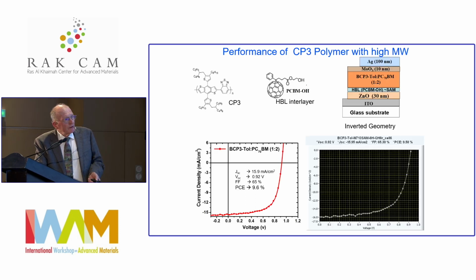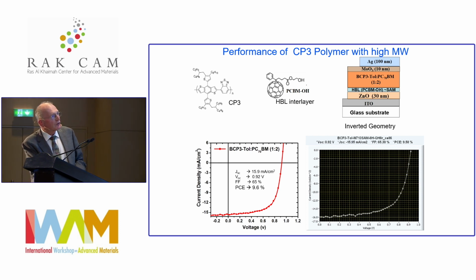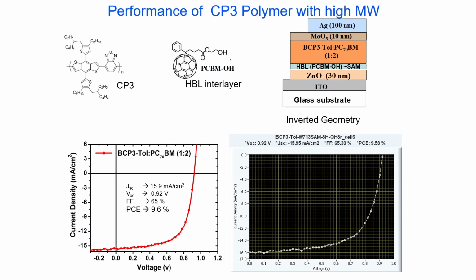And we pretty much made it, although the average efficiency was around 9.6%. But here's the structure of the donor polymer on the left. The fullerene is a hole blocking layer here. That's not the acceptor polymer. It's a hole blocking layer to facilitate negative charge extraction in this direction. And a blend of then the fullerene and the donor polymer. And we reached 10%, but the statistical average was 9.6%. So we made, we thought, the milestone to get paid.